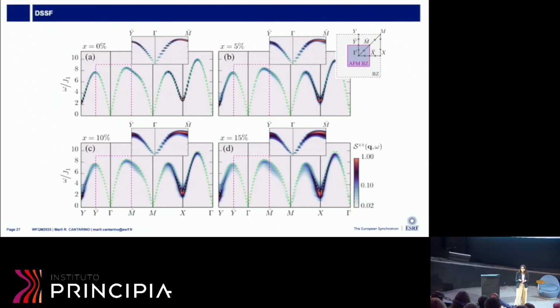For example, this splitting of the nematic size that I showed as a function of doping—I never saw any other study doing this for the doped samples. I saw studies doing this for iron selenium, for the parent compound, but not for the doped samples. So I don't know, for example, what happens in the case of potassium and cobalt doping. There are many ingredients I don't know about. We can discuss more later.